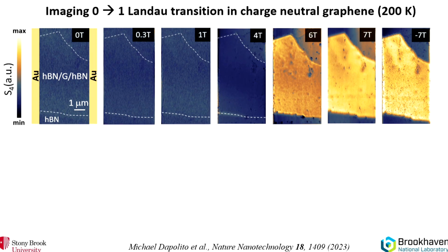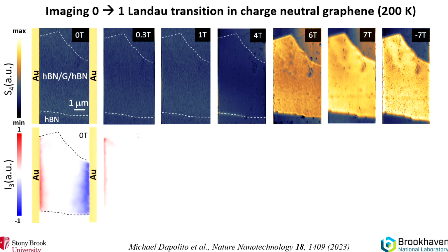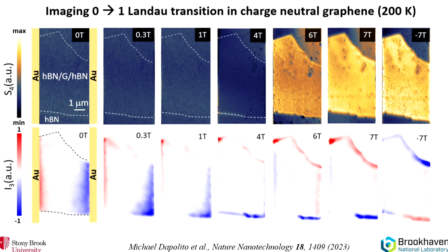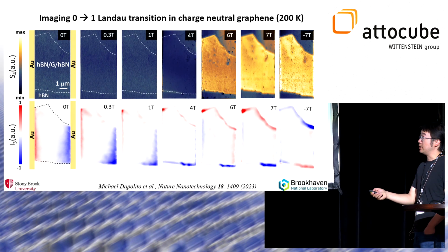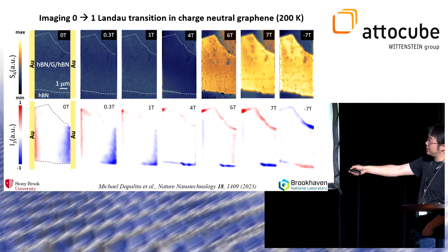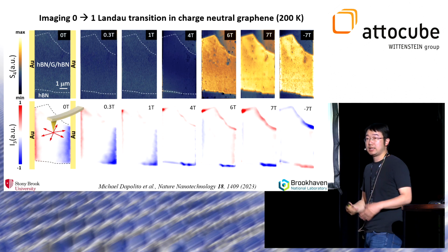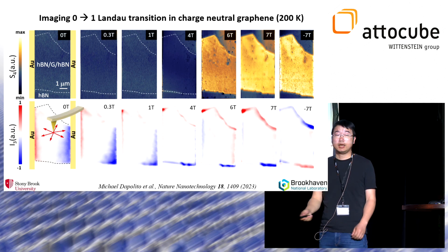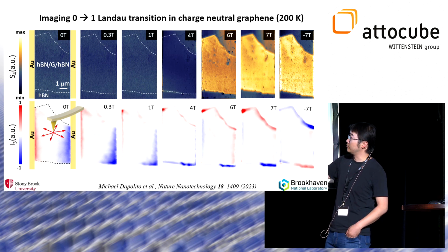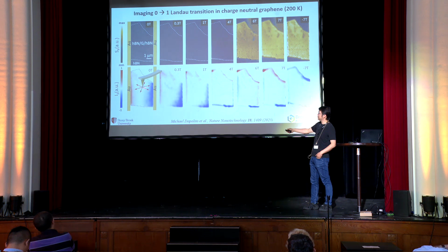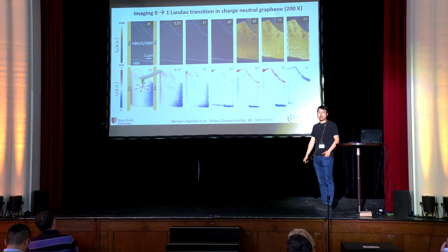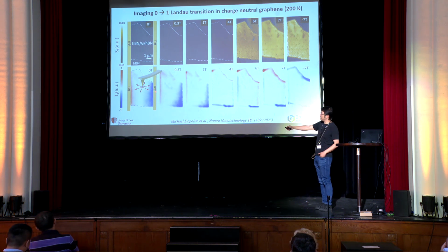And of course, we have electrodes on it, so we can measure the photocurrent, right? This photocurrent is measured by tapping this tip and detecting the modulated photocurrent through these 2 electrodes. You can see that at 0 T, you have this photocurrent concentrated at the 2 electrodes, which is understandable because at 0 T, you will have the so-called Seebeck effect. This Seebeck effect basically goes in arbitrary directions under the tip due to the heating. At this middle part, you will have an equivalent amount of current going to the left and right, so you will not detect any photocurrent. As your tip gets closer to 1 electrode, you can detect the photocurrent in one direction or the other.